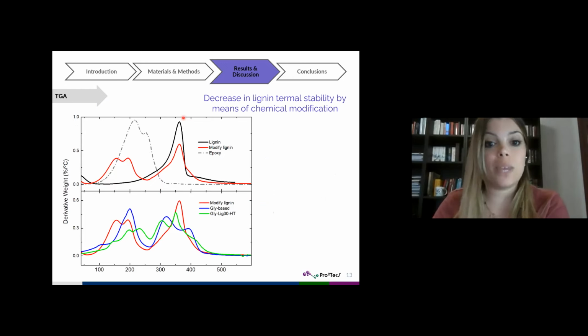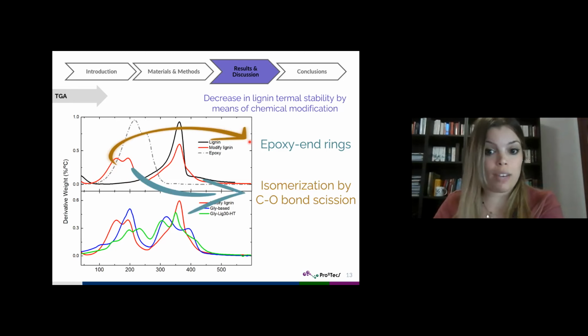The chemical modification of lignin gave rise to a decrease in its thermal stability due to the introduction of the epoxy compound in its structure. And as we can see, two new degradation events were found in this curve for epoxidized lignin, which can be related, the first one, with the existence of free epoxy rings available for further reaction, and its isomerization by means of C-O bond scission when producing the epoxy ring opening.